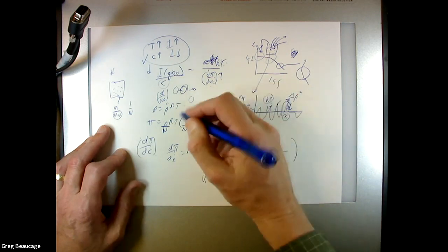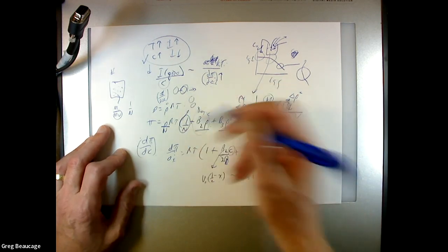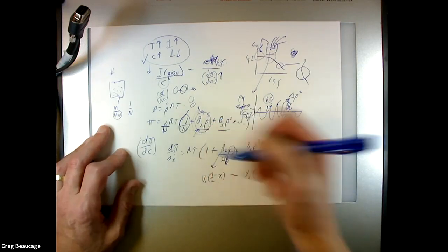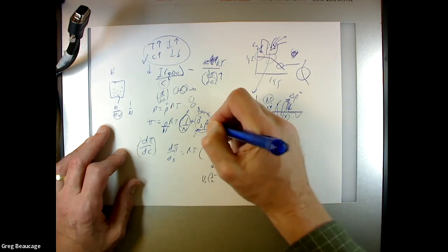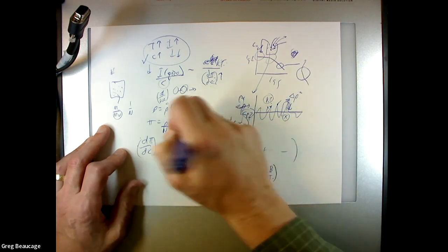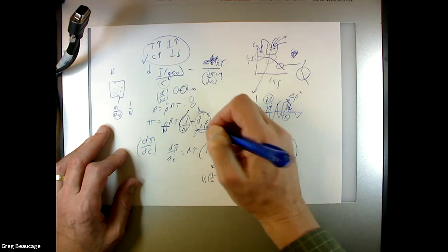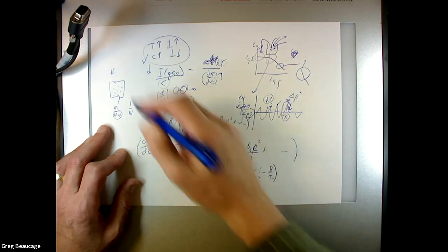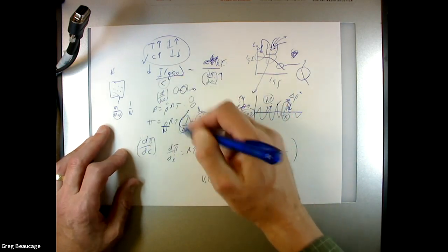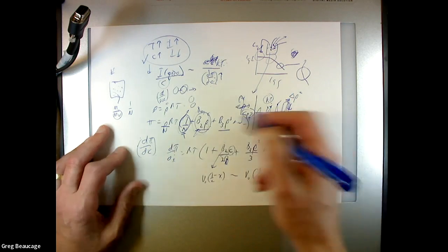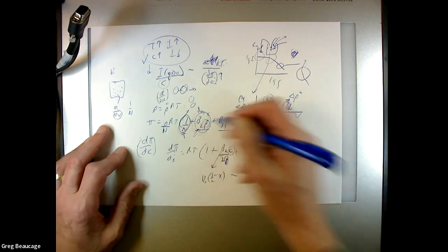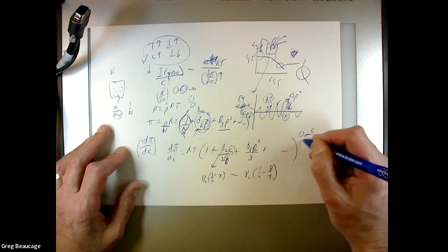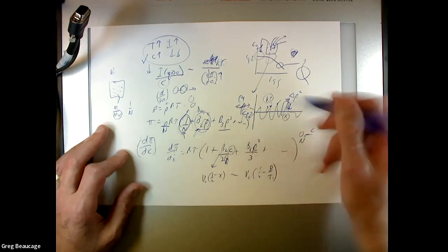So this thing is 1 over N for the first term here. This is how it works out. This term basically becomes like 0 because N is 100,000, and this B term kind of dominates the thing. But if you go to 0 concentration, you can get the number average molecular weight from this, if you do a concentration series. So that's kind of how this works. You can get the molecular weight of the chain from this plot. If you can extrapolate to 0 concentration, then you get the molecular weight.